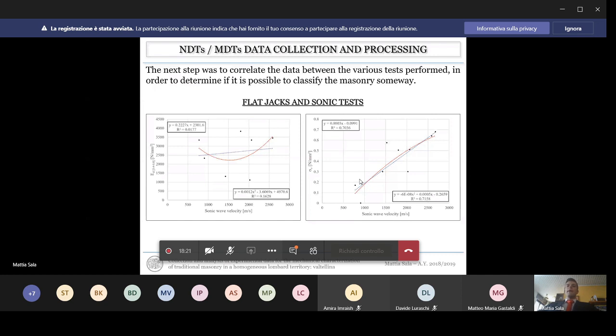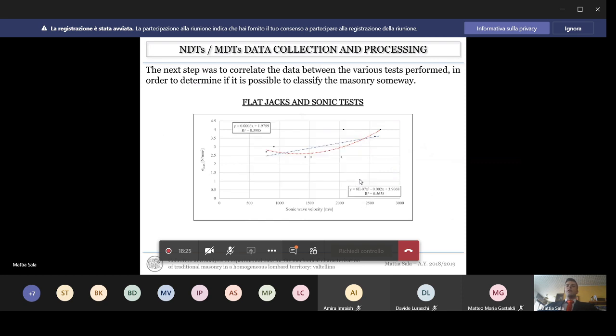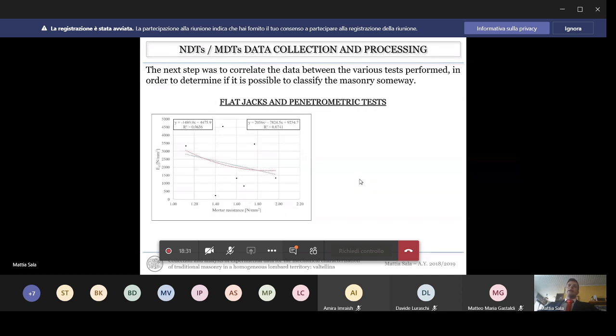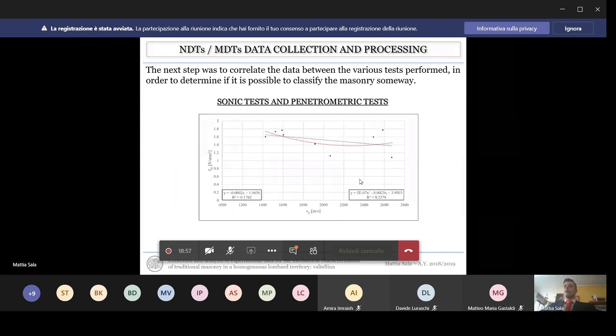In the case of the compressive strength versus the sonic wave velocity, also in this case, there is a scarcity of relationship between the data. Going on and analyzing flat-jacks and penetrometric test, we see that the lack of correlation highlights the fact that the strength of the mortar is not a useful parameter to evaluate the properties of a masonry, and also adding the parameter of the mortar quantity evaluated and shown before, the scattering of the points is really high. The last one was the correlation between sonic and penetrometric test, but even in this case, there is a poor value of relationship. This is due also to the fact that the sonic wave propagation is really influenced by the difference between stone and mortar.